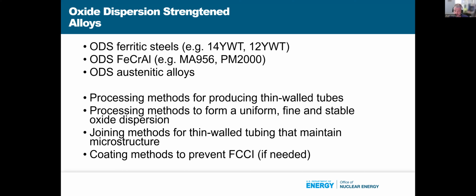Maybe you can take 316L, which we know has high void swelling rates at the intermediate, 400 to 500 C temperature range. Can we make it with an oxide dispersion that can actually address the void swelling concern, and still then have a lot of the other benefits of austenitic alloys like ductility and other things, or ease of making it into tube form? So ODS austenitic alloys would be in this area as well.